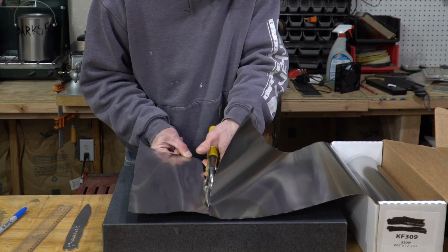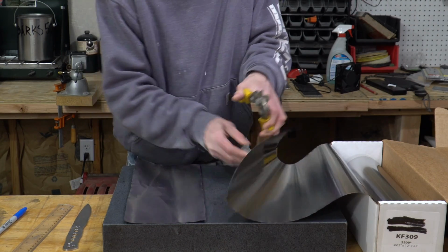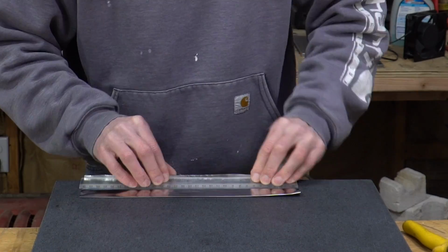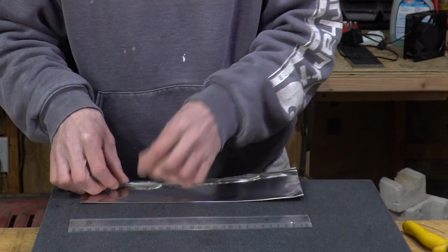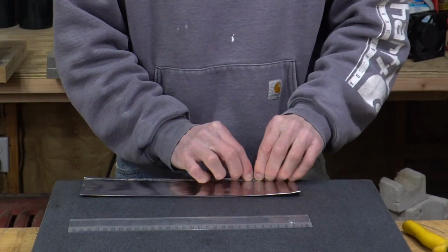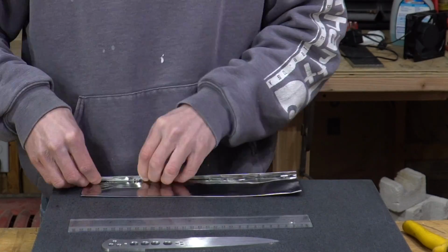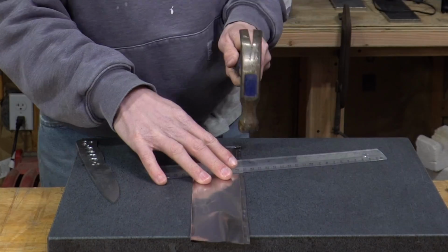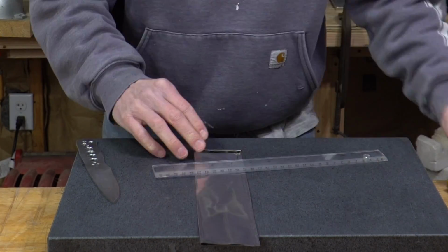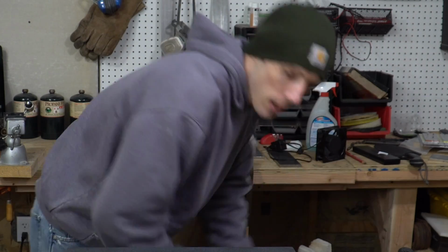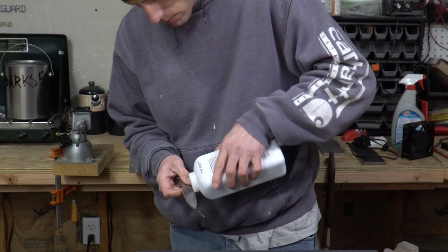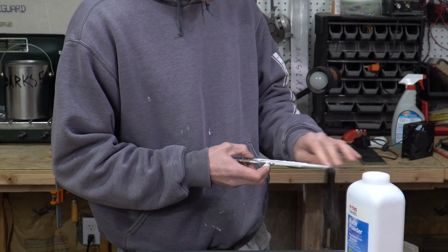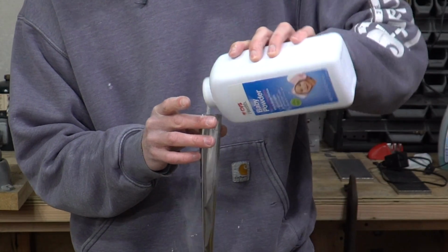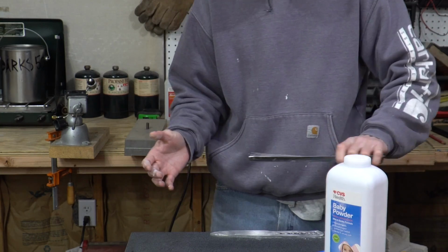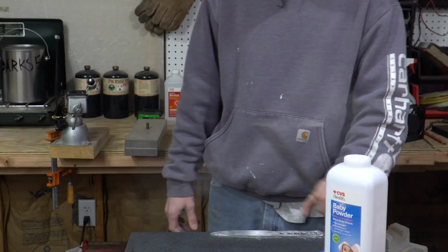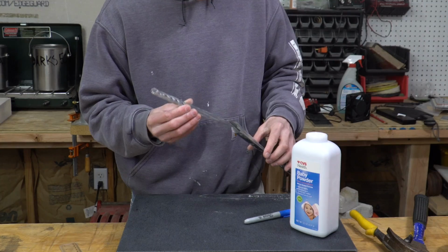First thing I'm going to do is cut off a 6-inch piece. Then we're going to fold it in half and then double fold both of the ends in order to make a packet. It's important to make double folds so that the packet itself is airtight. And then I use a hammer to tap down and further crease the folds in order to make 100% sure it is as airtight as possible. Next, I coat the entire blade in baby powder, and I add a little bit of baby powder, keyword here, a little bit, inside the foil packet to coat the inside of the packet. The baby powder will help keep the blade and the foil from welding itself together at higher temperatures.